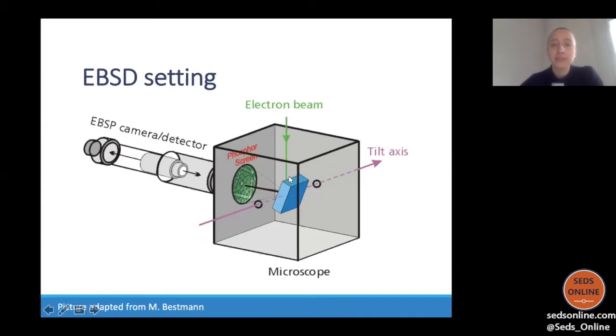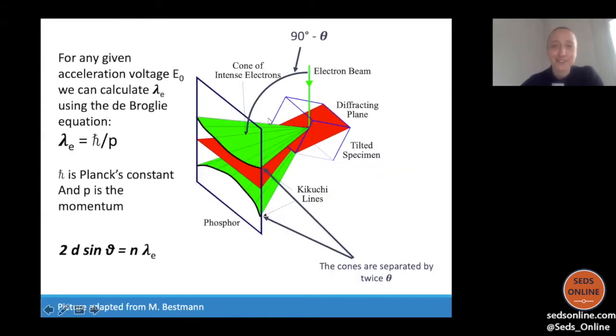EBSD is a method that can be fitted to most SEM microscopes by adding a special detector. And we shoot an electron beam on a sample, and the sample has to be tilted typically by 70 degrees. So the electron beam comes from the top, it gets diffracted, and the diffraction patterns are registered on a phosphorus screen that is at the end of our detector. So that all sounds not too complicated, but actually we often run into many difficulties, and you will hear about them a little bit. So sorry, this is a bit technical, but I talk you through this.